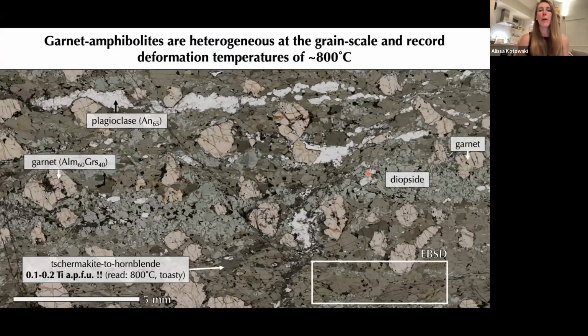So now we can look at some microstructures and start thinking about what's happening at the grain scale. So these garnet amphibolites are very heterogeneous. We have some of these relict layers of pyroxene-rich material here in this lighter green diopside. And you can see that there's not really any clear strain localization into one layer or the other. So the amphibole and the pyroxene actually seem to have relatively similar strains.